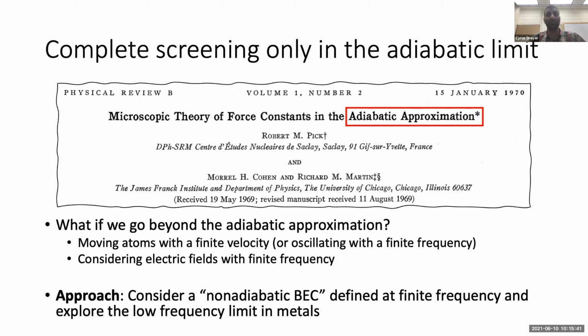But oftentimes in metals, we have to go beyond the adiabatic approximation. We have to think about atoms moving at a finite velocity or oscillating with a finite frequency, or consider electric fields or screening of electric fields at finite frequencies. And so that will be the approach that we'll take. We will consider a non-adiabatic Born effective charge, a Born effective charge that's not determined under the adiabatic assumption, which then has a dependence on frequency of atomic displacements. And then we will explore the low frequency limit of this quantity in metals to see if we can get a definition of a Born effective charge that's applicable to metallic systems.